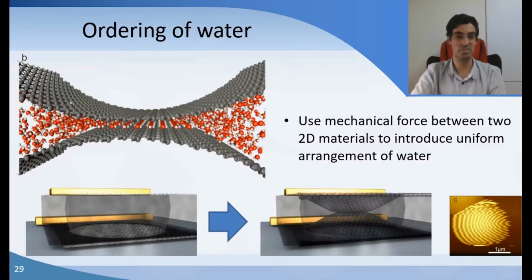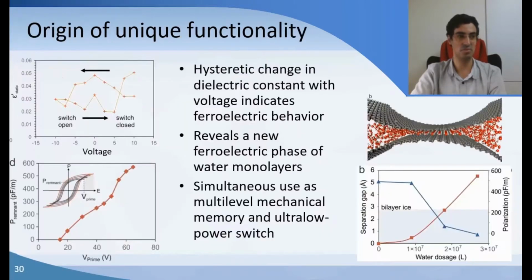What we're observing, however, is that we're getting a ferroelectric behavior. We're seeing the change of the static dielectric constant with voltage, so it's a sign of an increase in polarizability. And we also see that as the switch closes, the static polarizability increases. So it gets harder to reorient the molecules, which means that there's probably still water in there, but as we squeeze it, it doesn't have a lot of space to rotate. This might be the indication of why we're seeing a ferroelectric behavior, because water does have a dipole moment, right? It's just that normally you're not forming crystalline ice. So we're forming this layer, and it has a ferroelectric ordering.